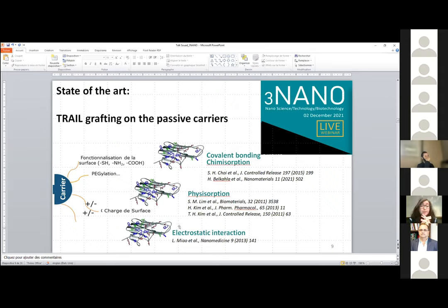So if we look at all these reports, several strategies were used to graft TRAIL on the surface of the particles. Some of them were based on covalent bonding using typically peptide coupling, attaching a carboxylic or an amino group of the TRAIL to an amino or a carboxylic group at the surface of the particles. Others used physisorption and weak interaction like hydrogen bonding, and others used electrostatic interaction. But in all these works, nobody was interested in the stability of the links between the particles and the TRAIL, particularly in biological media. And they didn't check the robustness of these attachments.